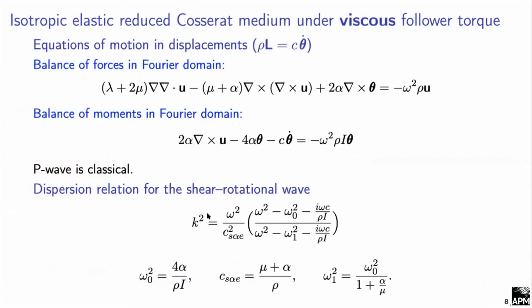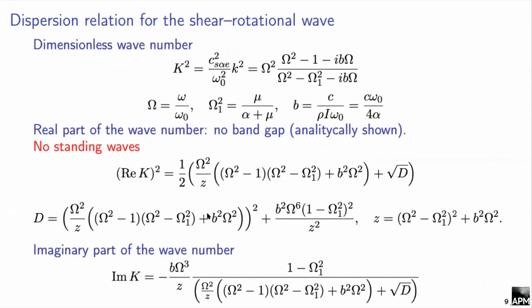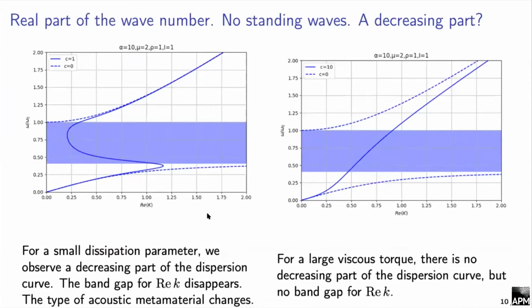What will happen if we have the viscous follower torque? Answering this question, we get the dispersional relation for the shear wave, but in complex variables. To avoid this, we made our wave number dimensionless and got the real part of the wave number and the imaginary part of the wave number. Analyzing the equation for the real part of the wave number, we see that the band gap will disappear. We observe the section of the falling dispersion curve and the disappearance of the band gap. This tells us that the viscous follower moment transforms a standing wave into a traveling but decaying wave.